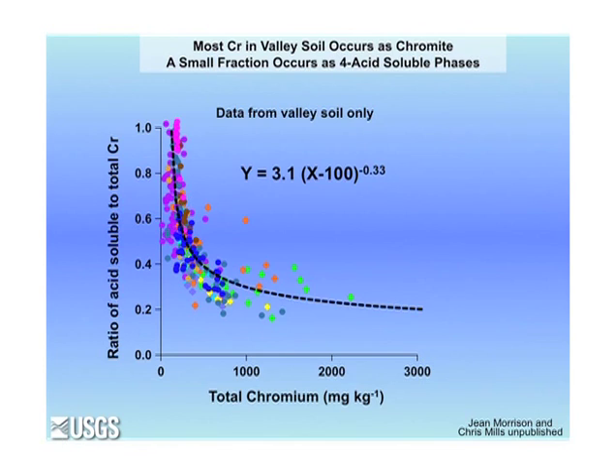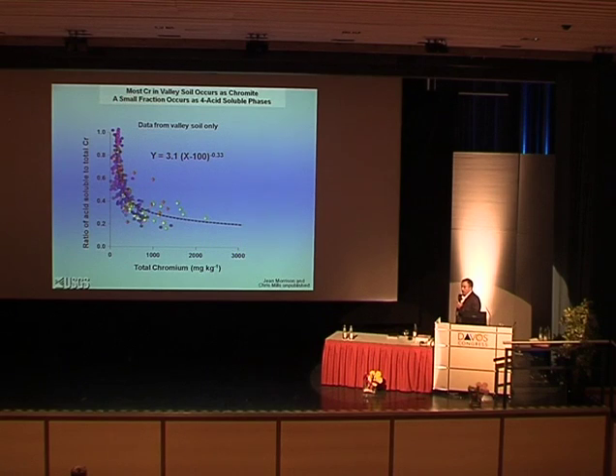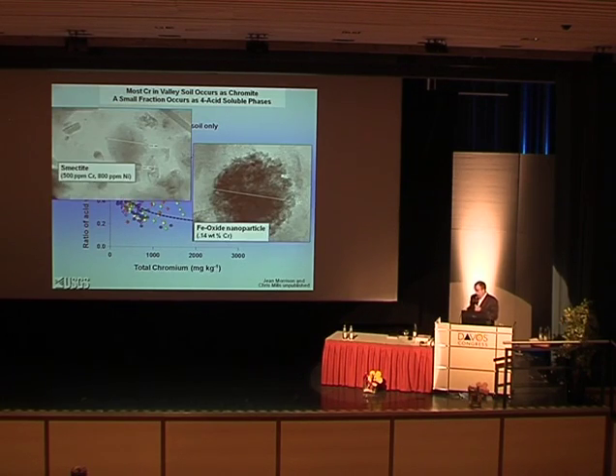A parabolic curve is indicative of a grain that's dissolving as a function of surface to volume ratio. As the grain gets smaller, the surface to volume ratio increases and the grain's more soluble in the four acids. So this fit is basically a parabolic fit with an exponent that comes out of assuming a surface to volume dependency. We also had to assume a constant background of 100 ppm of some material that's not chromite. And such a material is actually present in the samples.